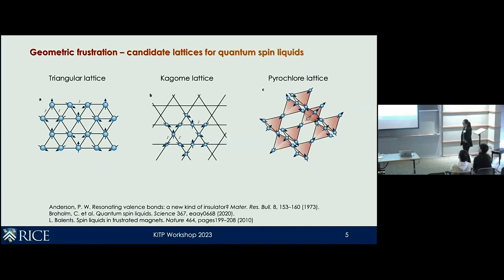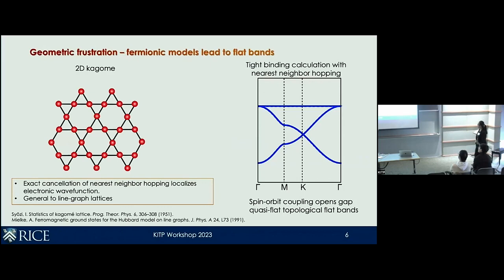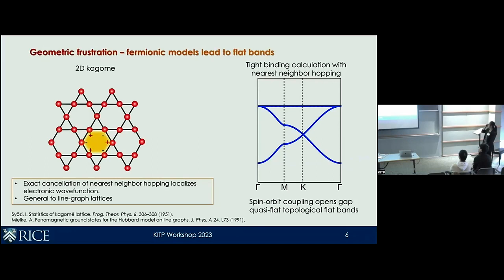Let me back up a little bit to give an overview of geometric frustration. As is well known in the field of quantum spin liquids, there are various types of crystal lattices where the geometry gives rise to magnetic frustration, preventing the ordering of moments down to zero temperature. For fermionic models, the same frustration translates to destructive interference of electronic wave functions, producing localized electronic wave functions in space, which become completely delocalized flat bands in momentum space. Including spin-orbit coupling opens up gaps, yielding topological flat bands.